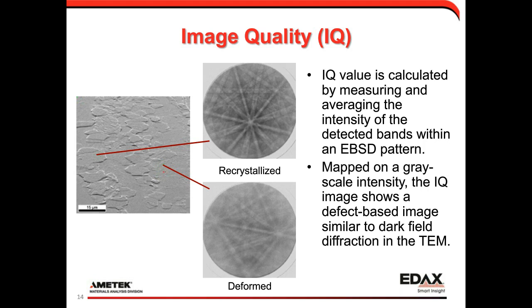So what we can do is measure an area and then map out these image quality values, where the lowest points are the darkest and the brightest points correspond to the highest image quality values. I've called this a defect-based type of image, kind of similar to dark field imaging.